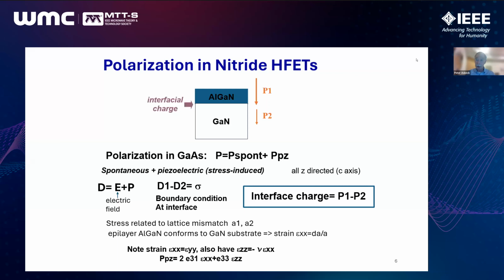Polarization stems from both the piezoelectric effect. In fact, gallium nitride has very high piezoelectric polarization coefficients, almost on a par with materials that are selected exclusively for their piezoelectricity. And there's also a spontaneous polarization like exists in ferroelectrics, except in the nitrides, it's not switchable. So these polarization vectors are directed perpendicular to the wafer surface. They form a difference at the interface between the two materials. Polarization is part of the electric displacement field, the D field. And according to Maxwell's equations, when there's a difference between D fields, there's a charge density, and that interface charge drives gallium nitride FETs.